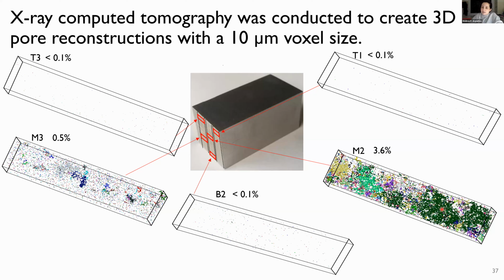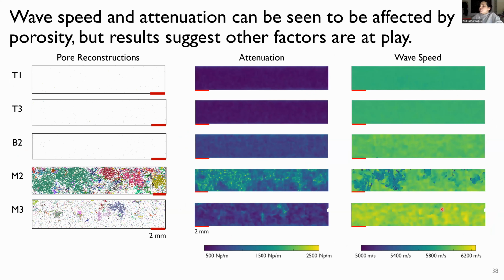So we went ahead and did our same ultrasonic measurements as before, so thickness independent wave speed and attenuation mapping. And what you're seeing for the pore reconstructions now is that they're simply oriented in the plane that the wave is seeing them in. All of these measurements were longitudinal waves that were normal to the surface. So we essentially just reoriented the maps so that we could look one-to-one at the relationship between that and some of the ultrasonic parameters.